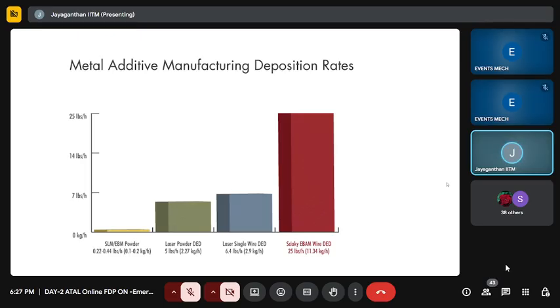That means one single machine, the way it has been designed, you cannot use for 3D printing any kind of material and end up getting different sizes and shapes of the component. If you want to produce an intricate shape of the component, wherein internal features are only micron, submicron, you need to maintain a very, very low deposition rate. That's where, on the extreme left, you have to choose selective laser melting or electron beam melting. The way the machine has been designed, it only ensures a very, very low deposition rate. Only through a very low deposition rate are you able to maintain the smallest size features, micron to submicron.